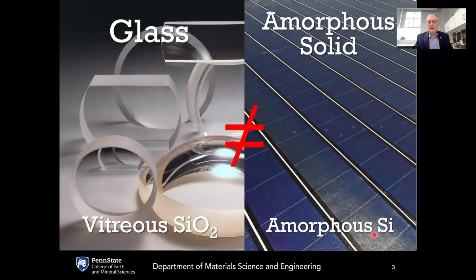So amorphous silicon has fourfold coordinated silicon atoms that are all bonded to each other. But the corresponding liquid, so liquid silicon, is sixfold coordinated. So the structure of an amorphous solid is different from the structure of its corresponding liquid because the coordination numbers are different, the short range interactions are different, and therefore there's no connection between the amorphous solid state and the liquid state, whereas there's a very close connection between the glassy state and its corresponding liquid.